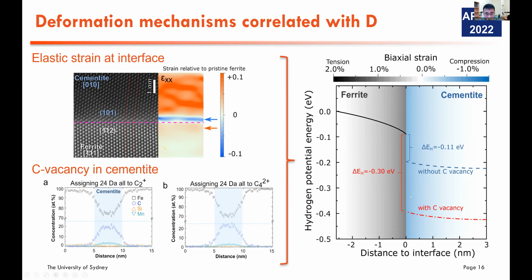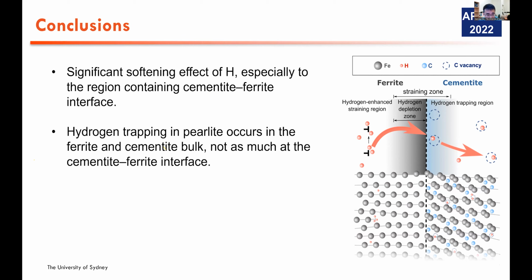This ultimately leads to our atom probe observations that hydrogen is trapped in and absorbed to cementite, creating a depletion layer in the ferrite phase next to the ferrite-cementite phase boundary. Okay, so here are the conclusions. A significant softening effect of hydrogen, especially in the region containing the cementite interface, was found. And hydrogen trapping in pearlite occurs in the ferrite-cementite bulk, not as much as we believed at the cementite-ferrite interface. That's it. Thank you.